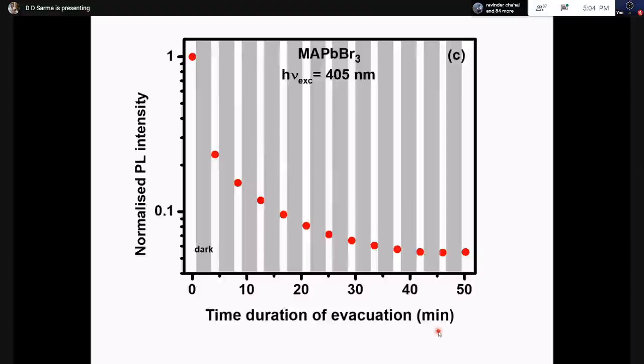And the reason it happens is that there are adsorbed materials on the surface which apparently passivate some defects, typically oxygen and some amount of moisture that are sitting on the surface of this material and passivating. Normally, dirt does not passivate, it kills the photoluminescence. But this is a very unusual material where the defects are partially passivated by this. And as I pump, these very loosely bound passivating agents get sucked out. And then these defect states become active.